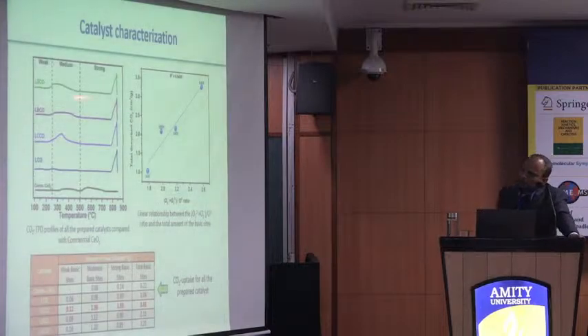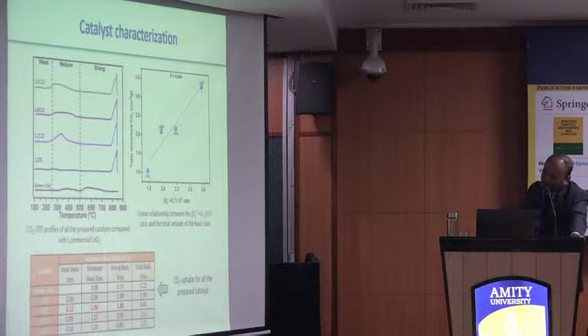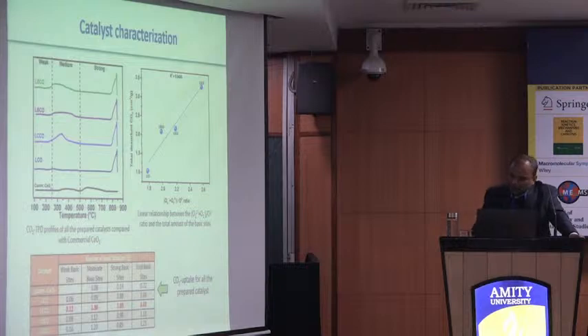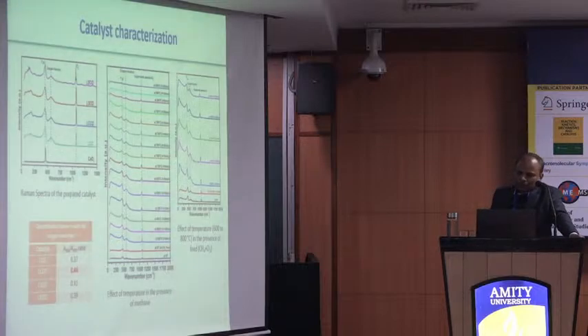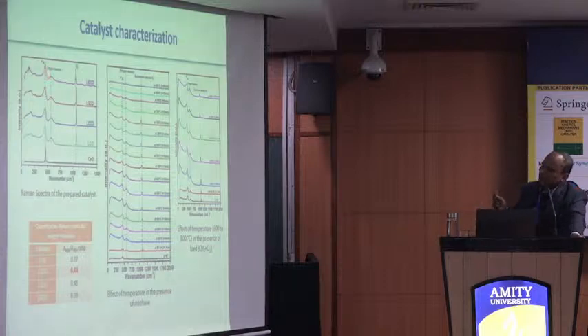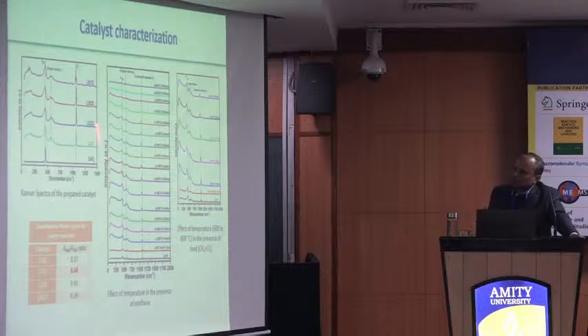We have also done the CO2 TPD to check the basicity, and it is showing a linear relationship against the oxygen uptake. You can see this value. The total basic sites is maximum for the calcium supported lanthanum cerium oxide. We have also done the in situ Raman. You can see here this is ceria, and the additional peaks are due to the presence of oxygen vacancy. This shows that with the incorporation of a basic metal, the oxygen vacancy sites are increasing.